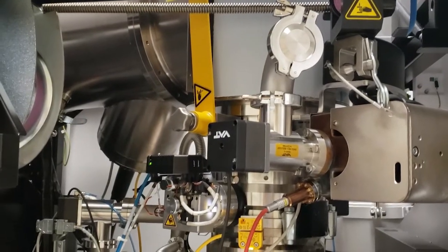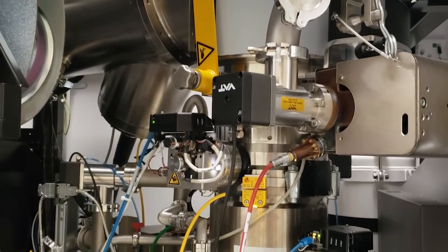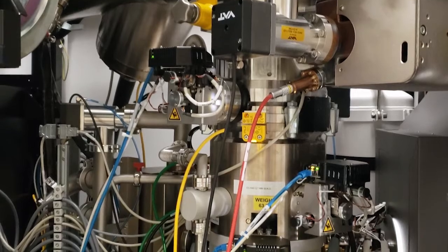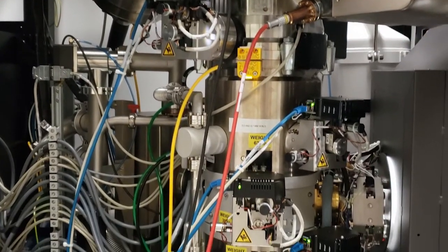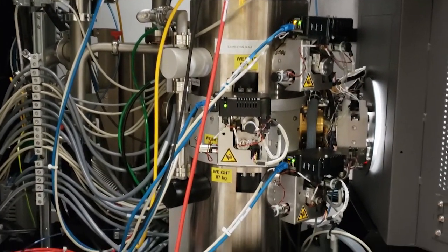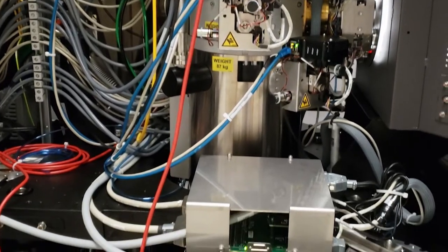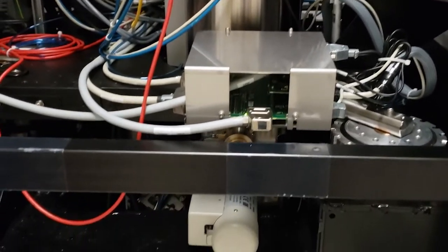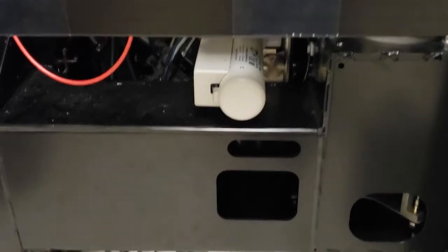The Thermo Fisher Talos is an analytical scanning transmission electron microscope powered by a field emission source under high vacuum. It is equipped with a Super X detector, so there are 4 EDS detectors that can obtain the chemical information of your sample. We can also capture images up to 4x4K resolution.